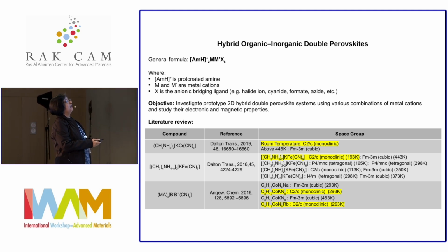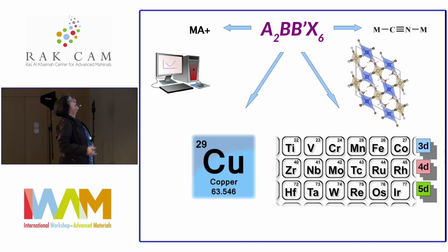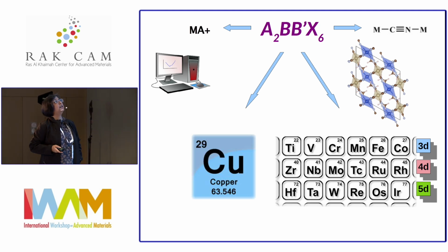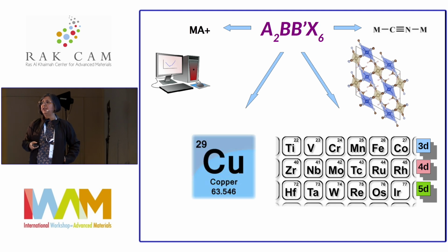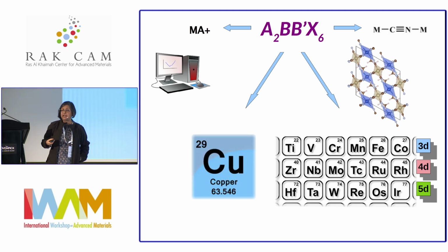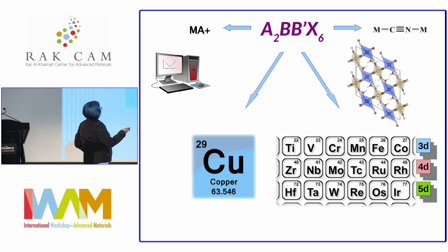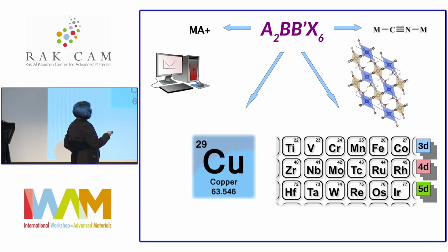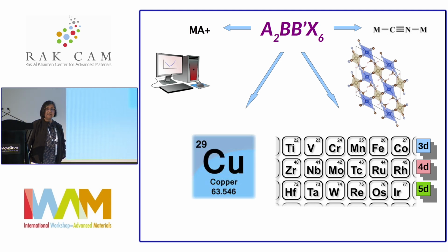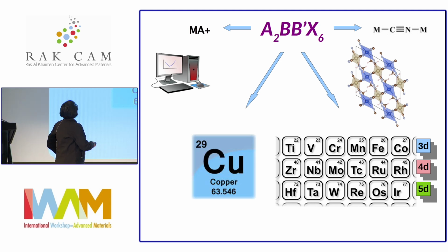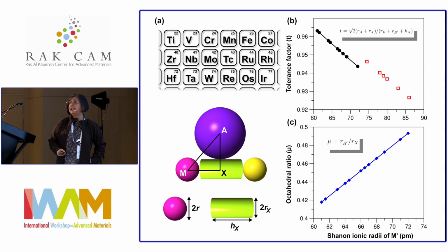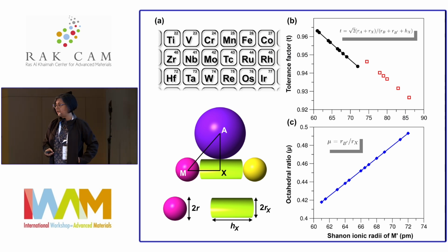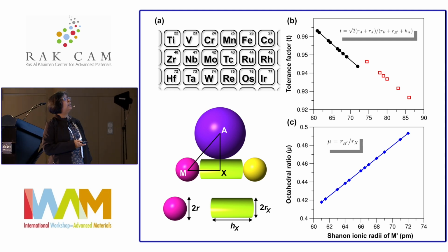And that's exactly the exercise we did. So we put at the A site the MA plus, and we considered the cyanide as the linker. And then for the B and B prime, we set copper, because with copper, maybe it's possible to make it monovalent. And then in the B prime, we had a choice of 3D, 4D, and 5D series, the entire series, and see what actually happens. Well, whether they will be formed or not in the perovskite structure, that depends on the tolerance factor.